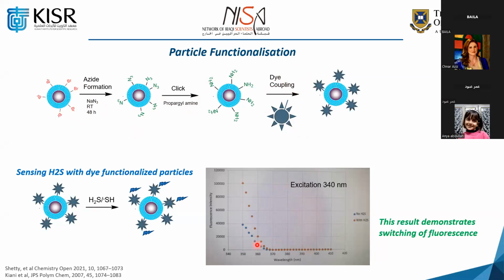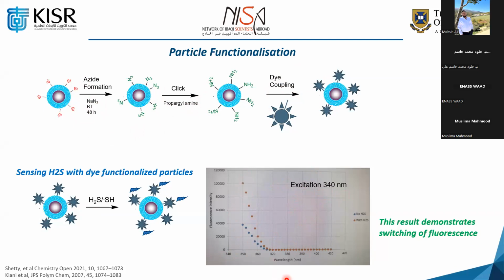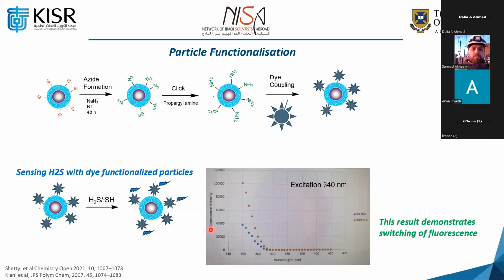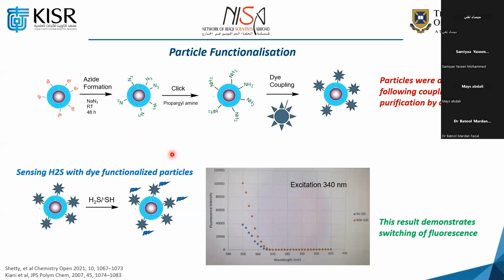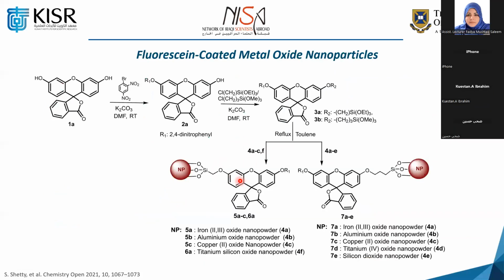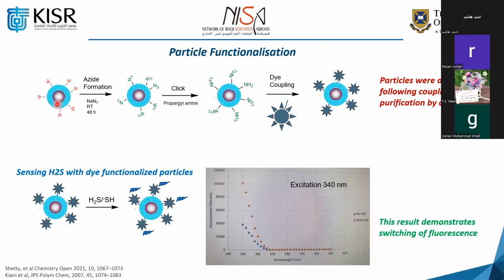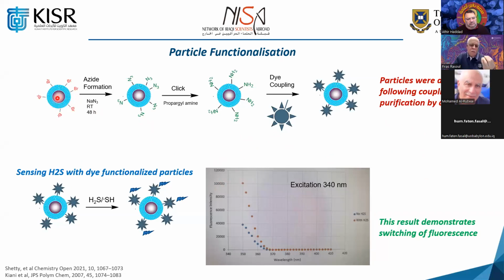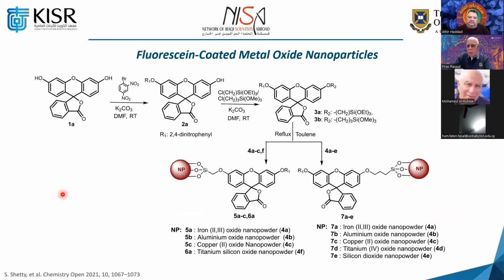And then, of course, we did some evaluation. You find here, we used excitation wavelength 340, and you could see the fluorescence result is quite substantial. And this is really what we use for that particular application. So by changing the particles from what I call soft nanoparticles, which are based on cross-linked polymers, we convert them to silicate type nanoparticles, to improve the performance under high temperature. So this is one of the applications which I mentioned.